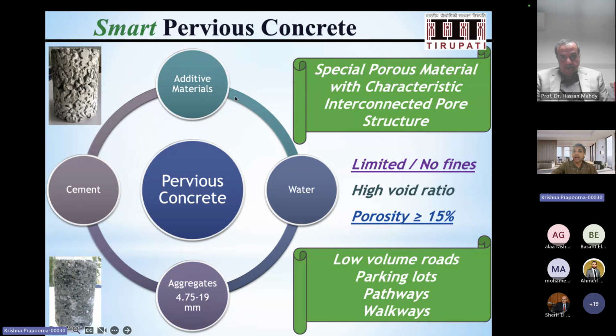You might start using additive materials such as supplementary cementitious materials, for example fly ash or silica fume, or maybe GGBFS, rubber granules to increase the strength of these materials, because it has very high void ratio. You can also expect that these materials are low strength because they also have interconnected pore structure. So what we have seen is this can be applied in low volume roads, parking lots, pathways, and walkways.